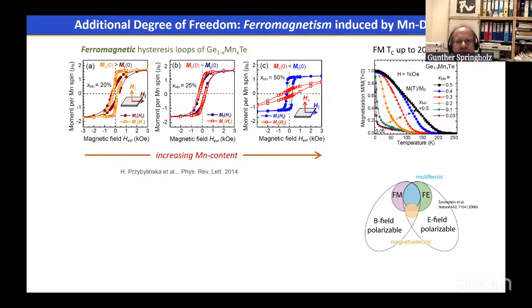Now, in this system there's also an additional degree of freedom, because we can also induce ferromagnetism in germanium telluride by manganese doping. This is shown here. If we measure the magnetization as a function of temperature for different manganese doping levels, we see a ferromagnetic signal emerging with a transition temperature that strongly increases with the manganese concentration. The maximum is 200 Kelvin for a manganese concentration of about 50%.